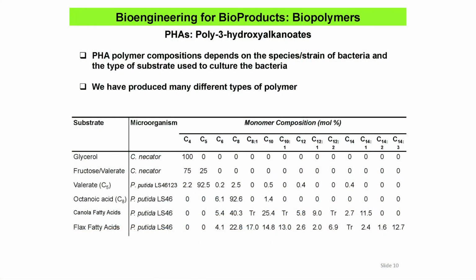So in my lab, we use different microorganisms and different carbon substrates to grow them, and then they produce polymers with different compositions. So for example, if we use this bacteria, Cupriavidus necator, and grow it on glycerol, or waste glycerol from biodiesel, we get 100% C4 chain. If we mix fructose and valerate, we get a mixture of 75 and 25. If we genetically engineer to change the enzyme that does the polymerization, we can make a polymer that's over 90% C5, a little bit of C4. And as we change the carbon chain, the subunit composition, we change the physical and thermal properties.